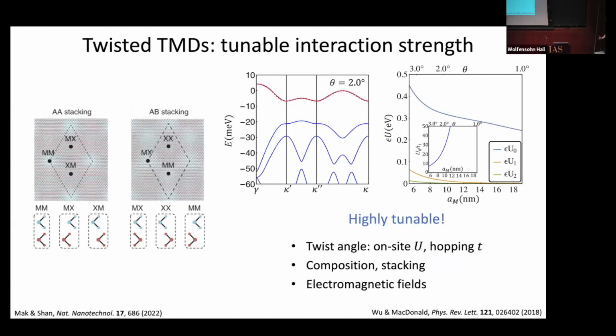So just like in graphene, as I described before, you twist two transition metal dichalcogenides together, and they form a Moiré superlattice. There are quite a bit of details that can go in, so it matters whether you have AA stacking or AB stacking that is naturally occurring. These layers alternate, so you break inversion symmetry in the layers, and so it matters whether you twist and stack parallel or anti-parallel. I'll be talking about this AA stacking case throughout this talk, but just to point out that there can be differences there. These Moiré superlattices are not actually equivalent to one another.